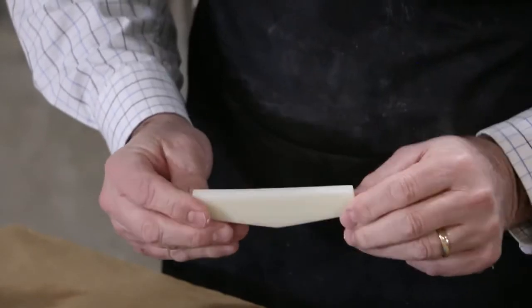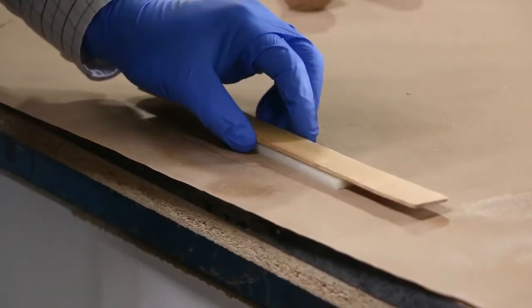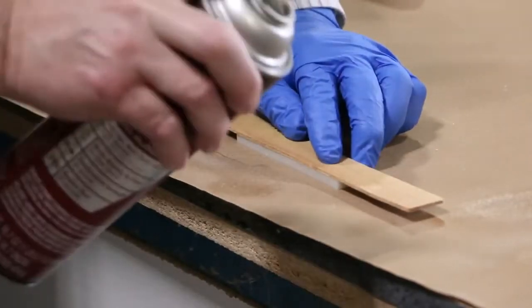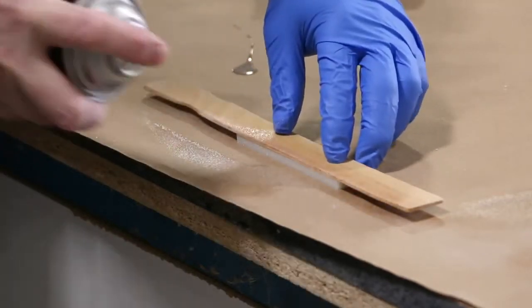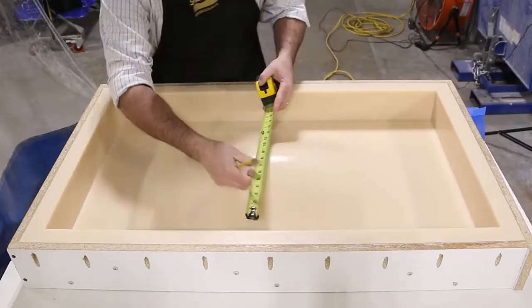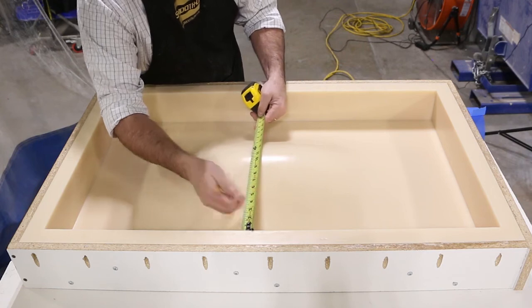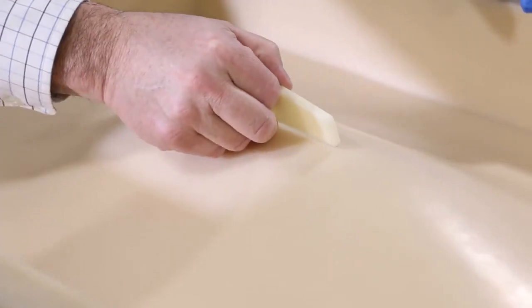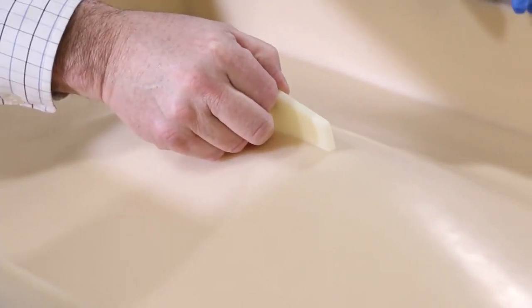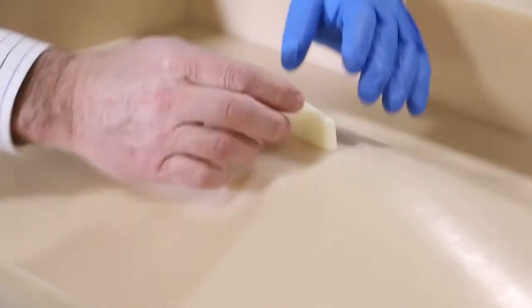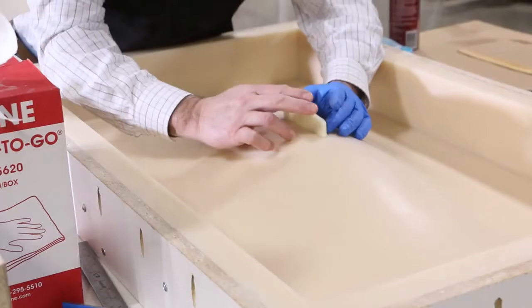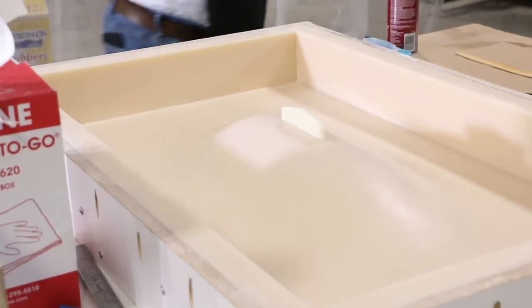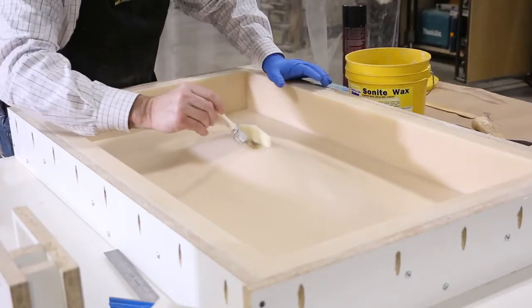Using a mixing stick as a mask, I sprayed contact adhesive on the bottom edge for attachment to the rubber sink mold. I then measured and located the correct position and attached the plug firmly. Sometimes straight pins can be inserted into the plug to aid with attachment. This may be necessary to ensure it does not become dislodged during concrete casting.